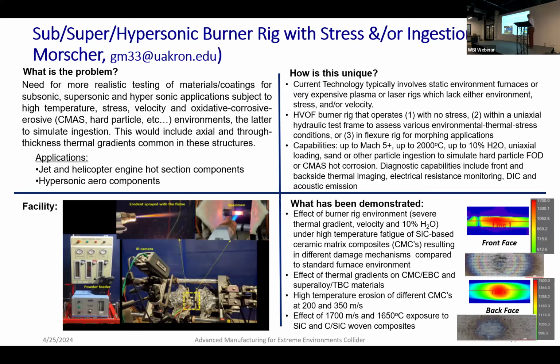So this kind of gives you an idea. This is a 1700 C front face. Back face is about 1500 C, so it's a 200 C thermal gradient. We've got thermal gradients through the thickness and in the axial direction. And we work a lot with modelers to try to understand material behavior and response with respect to the various conditions, as well as the damage that is incurred. Next slide.